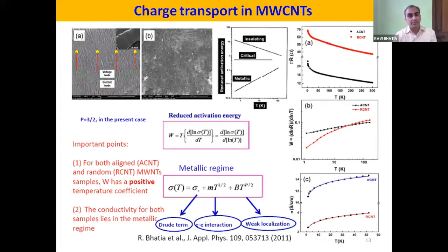The speculative answer can be given because we have not seen the samples used by the Yoshida group. It is found that the amorphous carbon gives rise to VRH conduction because of its quasi zero-dimensional properties. Here the carbon nanotube presents its quasi one-dimensional transport properties. So I believe that that result is correct, but it is not a very good sample that they have chosen to study the charge transport at low temperature in the multi-walled carbon nanotubes.